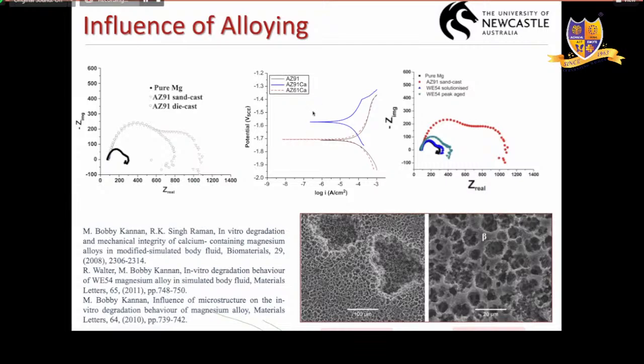Later on we studied adding calcium to it. Now, calcium is biocompatible. We know that one of the major components of bone is calcium. So we add calcium to see whether it influences or controls the degradation. And also, as I said, we looked into the rare earth elements as well. So, in a nutshell, what I could say from this slide is alloying improves the degradation resistance to some extent, but it's not sufficient enough.